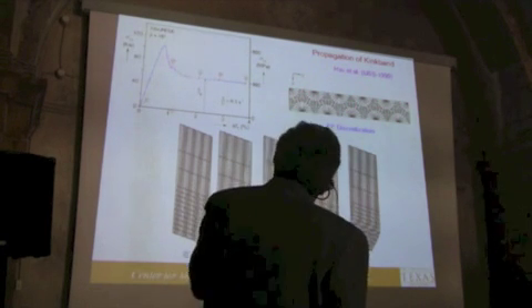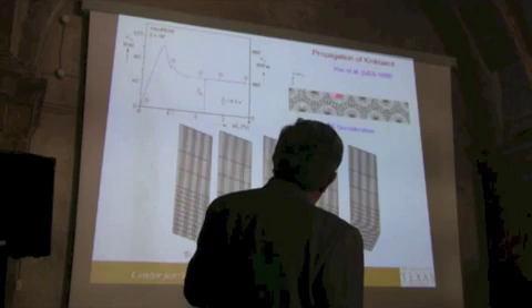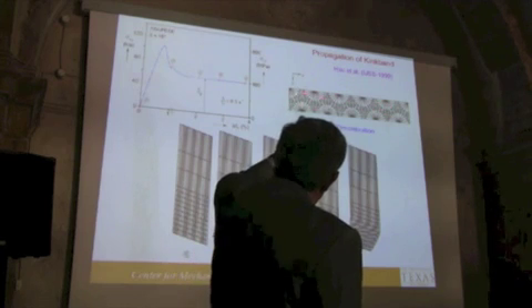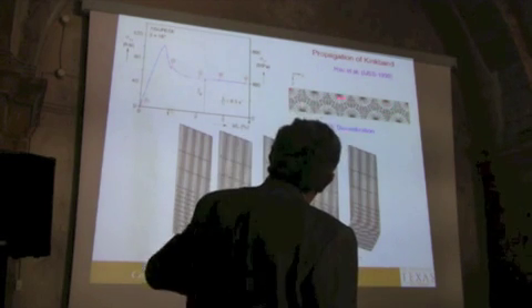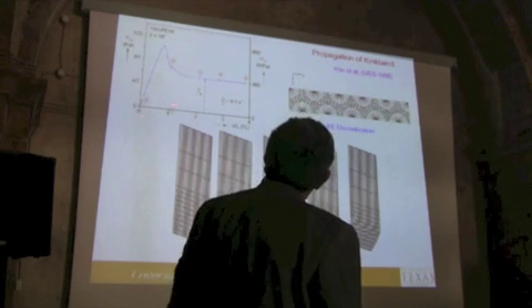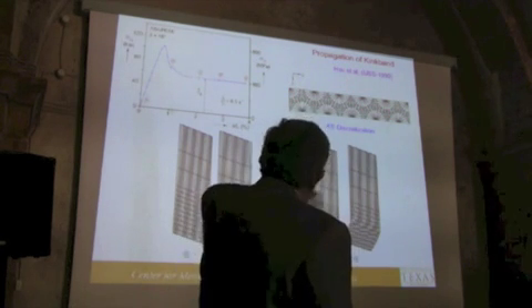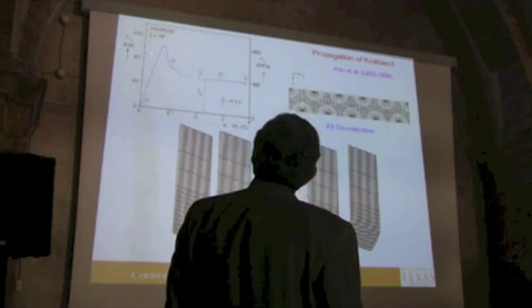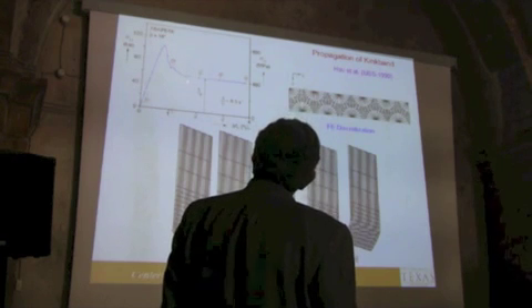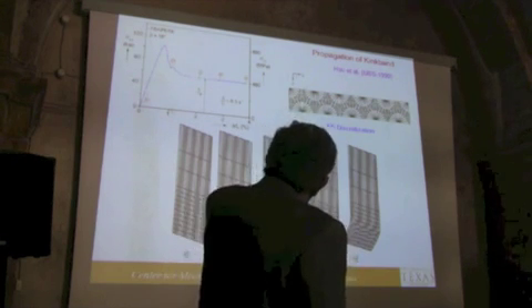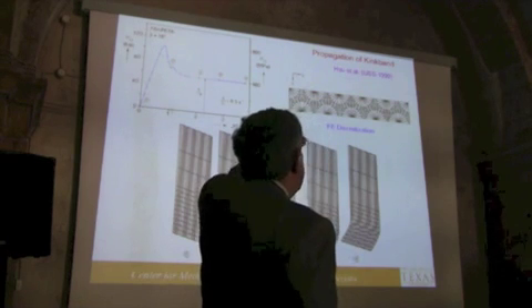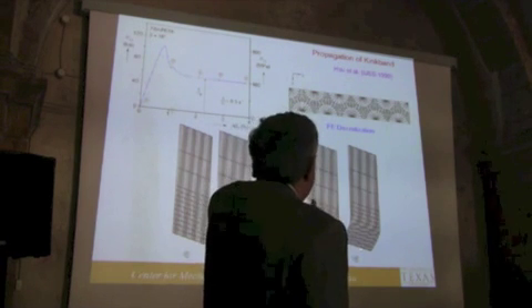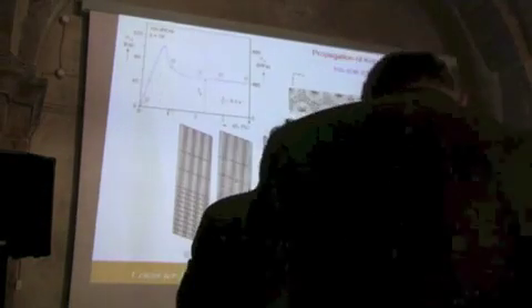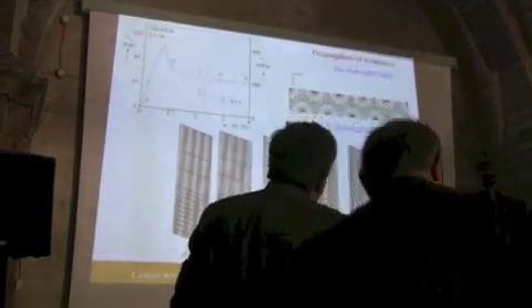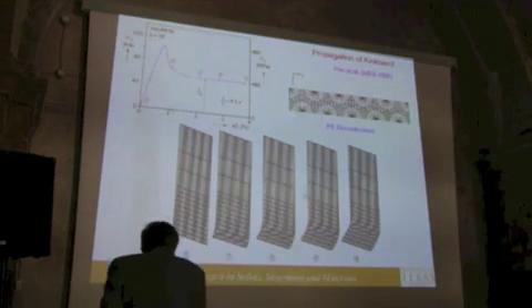Okay, so if you want to see the propagation, we'll develop a different model. Again, it's a brute force model where the fibers and the matrix are modeled in a 3D setting that you see here. You're seeing the top of the specimen, okay, with the proper properties, and with some details that I'm leaving out. If you compress it, you come up and then you come down, and then you see it propagating. Again, we don't have the breaking, but everything else is being reproduced. In other words, this rotation that you get and this angle that we introduced in the model.